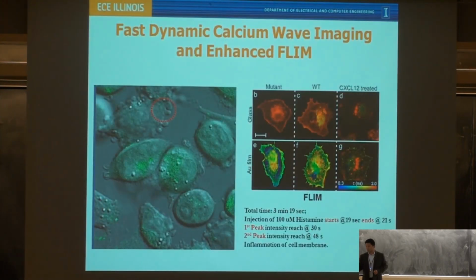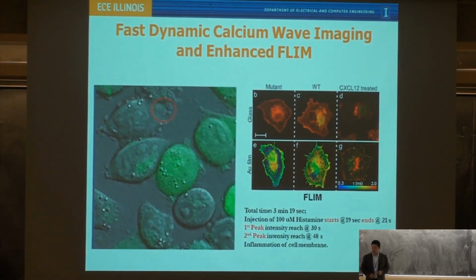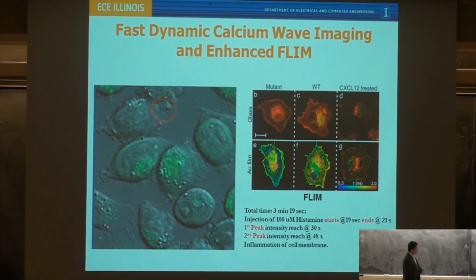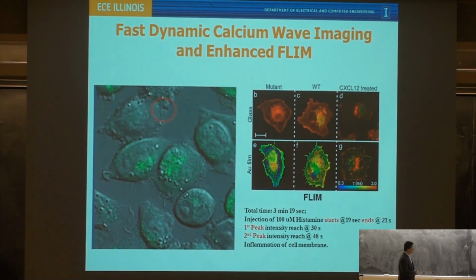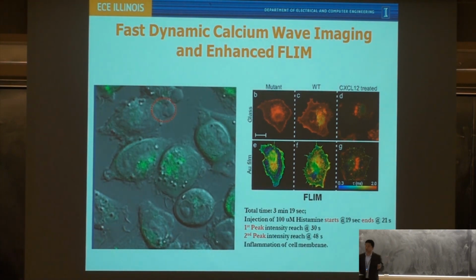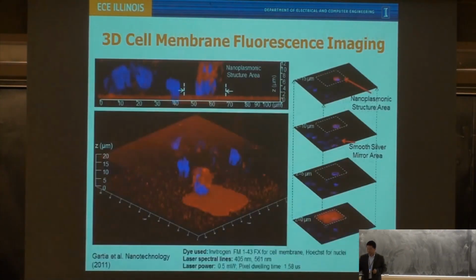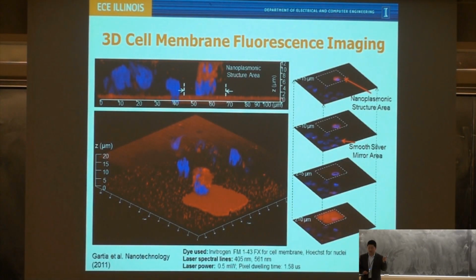All right. So what we are also trying to do is to see if we can do fast dynamic calcium imaging or enhanced fluorescent lifetime imaging. Because there's something I forgot to mention: when we do imaging, we use a confocal system in IGB. We use the shortest possible integration time for each pixel. That also brings us another benefit besides the sensitivity boost, which means that we can reduce the photo damage to the lowest levels, because we let the photons reside in one pixel for the shortest time.